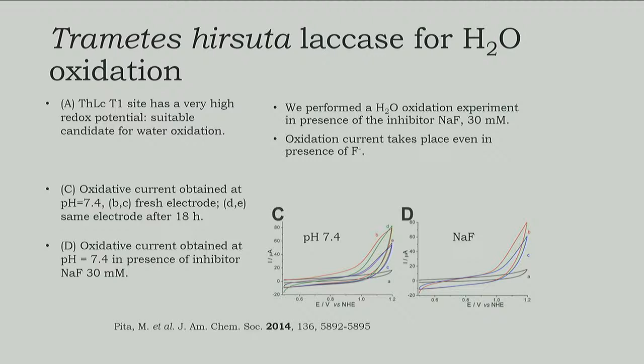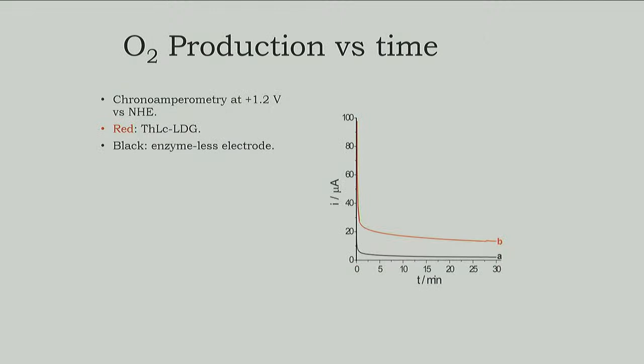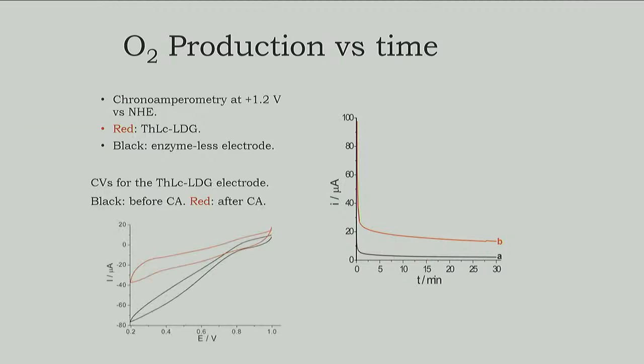We also tested how it reacts if we put in a natural inhibitor. This fluoride is going to sit in the path of the electron transfer inside the enzyme between one of the two active sites, but it didn't affect at all. It was giving the same response. So we assume that only one of the active sites was involved in this reaction. After half an hour, we can see that the currents are higher, and we have to find a way to measure if these currents correspond to oxygen or not.